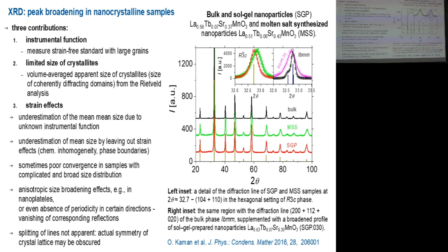And also there are strain effects, like as I mentioned, if you have some solid solution and the composition inside the solid solution varies in your sample, like it slightly varies between individual nanoparticles, like the lattice parameters of individual nanoparticles will be different, and it will cause some minor shifts of the Bragg diffractions in the pattern. So that's why there is this broadening related to the chemical strain or to the chemical heterogeneity.